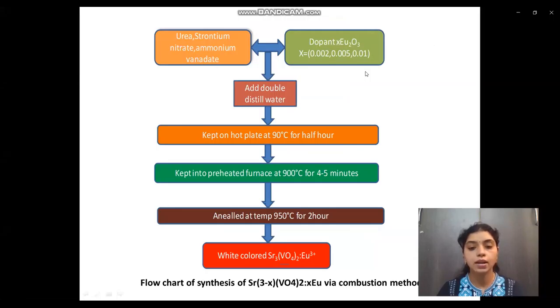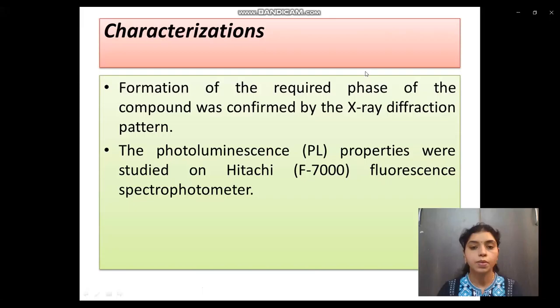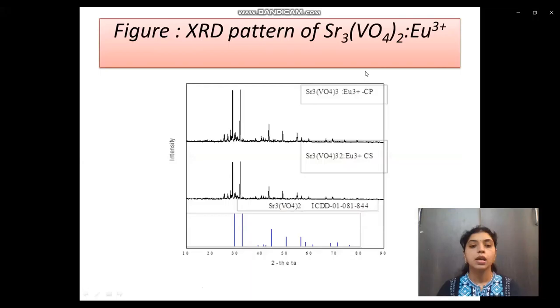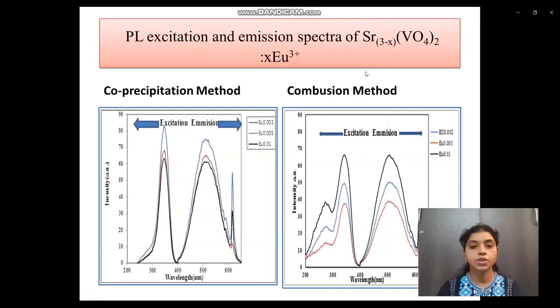Then characterization was done, that is XRD and photoluminescence properties. This figure shows the XRD pattern of this product, which is well matched with the standard file for both the combustion method and the co-precipitation method. This is the PL excitation and emission spectra of this strontium vanadate doped with Eu3+. By the co-precipitation method, the excitation maximum intensity peak is at 350 nanometer, and the emission is obtained at 520 nanometer and a sharp peak at 613 nanometer, with the maximum intensity at